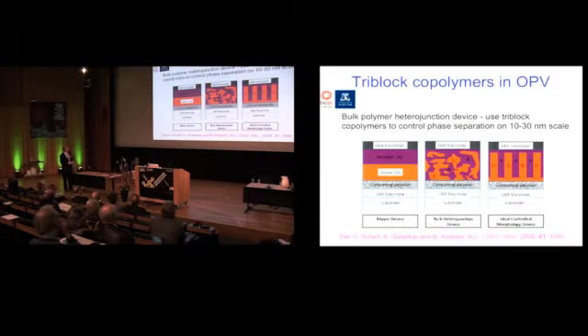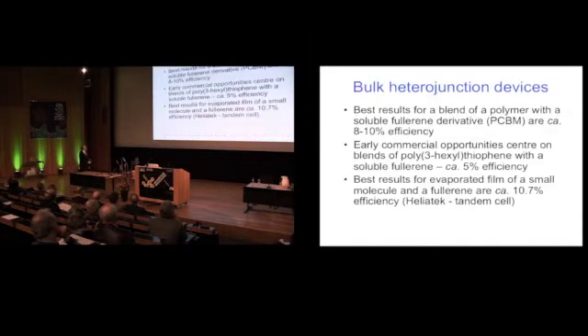So you want a perfect blend, and people think this geometry might be the best, this interpenetrating network of donor and acceptor polymers. But it's quite hard to make that in the laboratory, although in Japan, the Mitsubishi company has recently done that. So the best results for polymer solar cells with a buckyball, a fullerene, are 8 to 10% on a tiny cell, 10 postage stamp size. With polythiophene and fullerene, you can get about 5%.